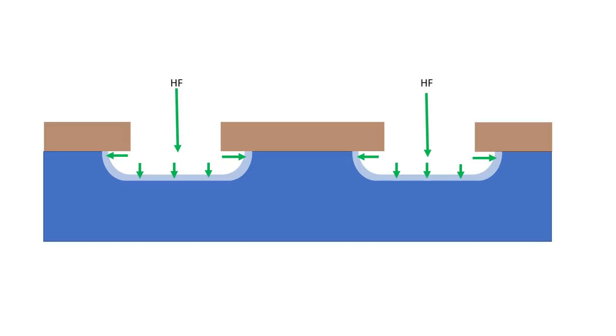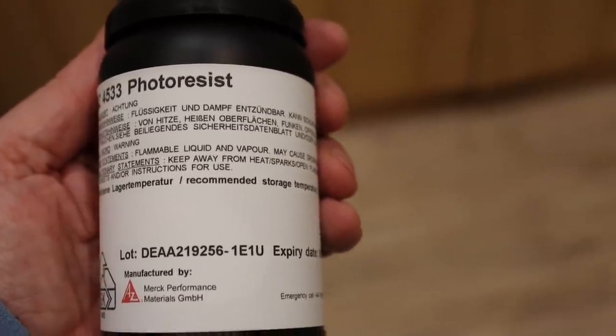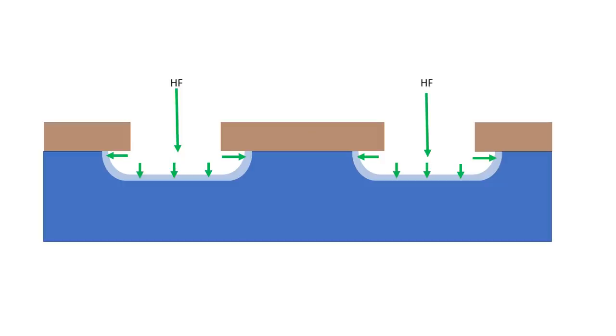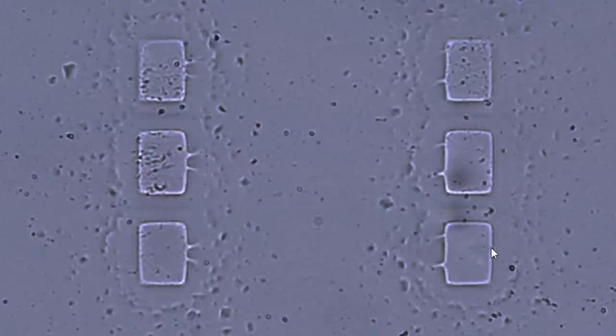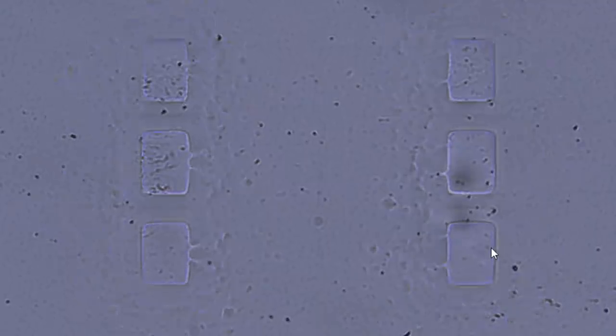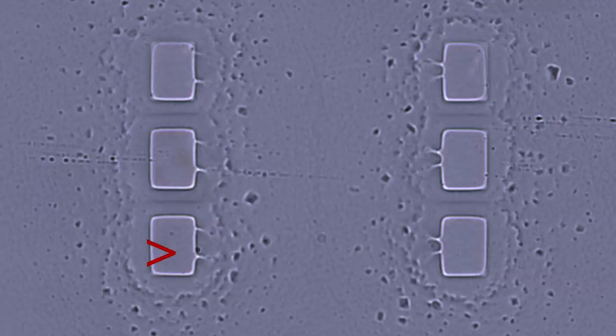If you want to etch glass surfaces in a specific pattern, you need to partially protect the surface with a material that can withstand the etchant. And for this we have a few different options. We can for example use photoresist, which is a photosensitive polymer that can be applied from solution and can be patterned by using selective light exposure. But photoresist can protect the glass from HF only for a limited amount of time. And the reason is that, because HF is such a small molecule, it can also quickly diffuse through the organic resist material, which is generally only a few microns thick. Once the HF has diffused through the layer, it will start reacting with the glass and at that point the photoresist loses adhesion and releases from the glass. So the trick is to make photoresist thick and in addition make it adhere very well to the glass. Otherwise, the HF can just creep directly between photoresist and glass from the sides. And here you see this effect in action, where HF has gotten under the photoresist layer.